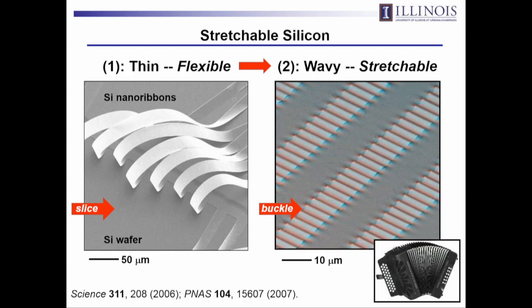and we've integrated onto its surface an array of very thin silicon nanomembranes, but not in a flat geometry, in a wavy geometry, sort of mechanically buckled, so that the hard, soft, integrated material system that you have here essentially has the elastic properties defined by the underlying rubber substrate, but with the electronic properties defined by the silicon, in an overall system that affords a physics that's very similar to that of an accordion bellow. So if I take this thing and I stretch it out, the wave structures in the silicon can change to accommodate that applied strain without fracturing the silicon, which in fact is still a brittle material. As you stretch it out, the wavelengths of these buckled wavy geometries go up, the amplitudes come down, in a way that affords linear elastic mechanics.